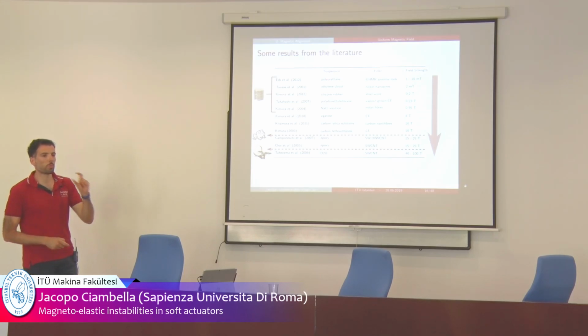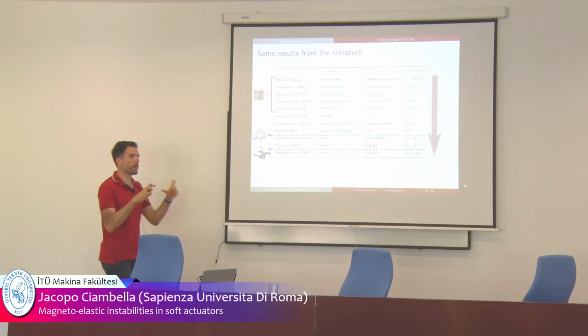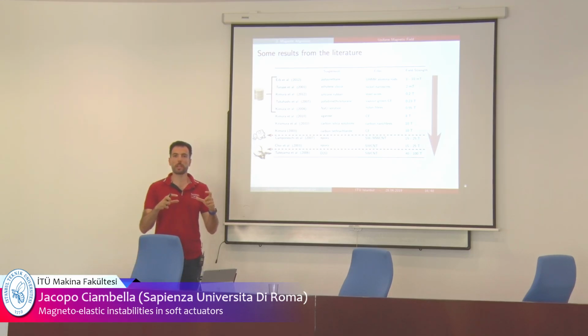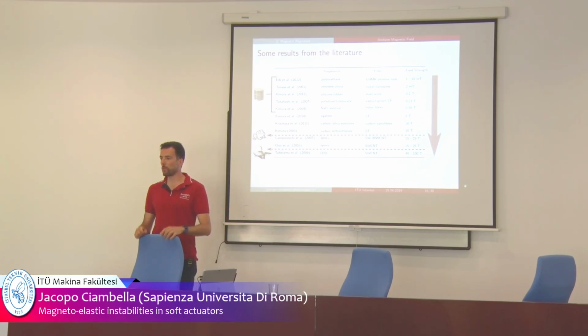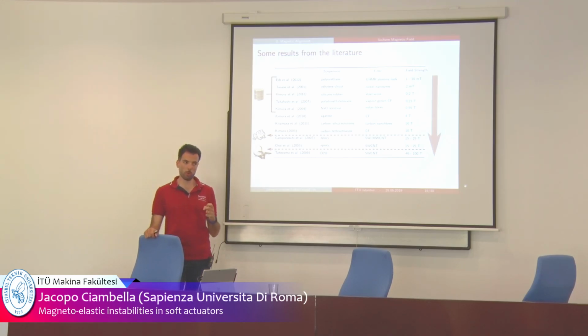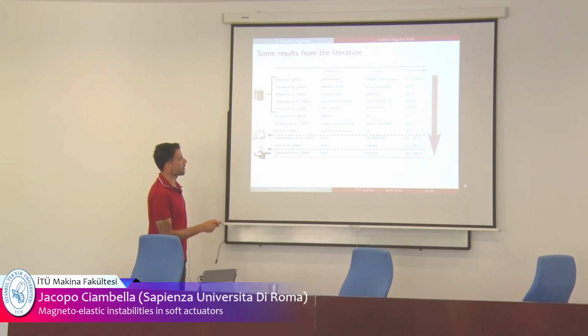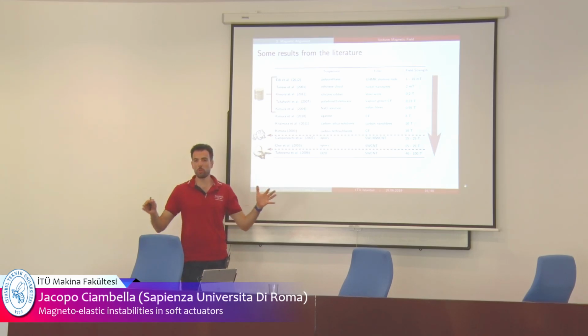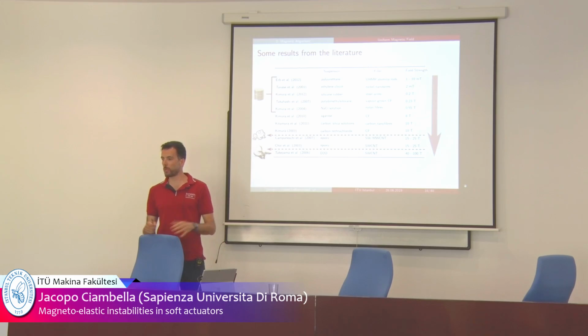So now consider that with a proper assembly of cylindrical neodymium magnets, which are quite strong magnets, you can obtain fields up to 0.1 Tesla, let's say no more than 0.1, probably even lower. And so this is what is done here. Then 8 Tesla is extreme, you need a huge equipment to obtain 8 Tesla.